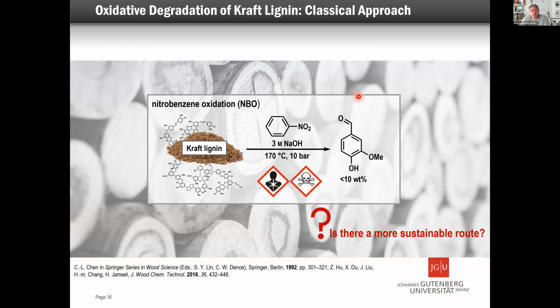But also an aroma chemical. There's a standard reaction which is used quite often, nitrobenzene oxidation, and nitrobenzene oxidation has the highest yield you can usually obtain, but you cannot use this for production because you reduce the nitrobenzene and you make a variety of carcinogenic and toxic compounds. Therefore it's just a standard reaction which tells you how much vanillin can be taken out of the relatively diversely connected lignin polymer.